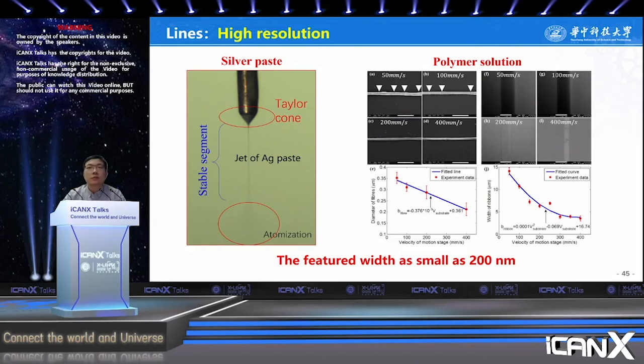However, for the honey-like solution, one can use both the stable segment and the high-speed motion stage to directly write pattern. And at the same time, the high-speed motion stage can further reduce the diameter of the jetting and easily reach sub-micrometer, such as 200 nanometer. Another important feature is to control the cross-section shape from the circle. This is circle fiber to thin film by adjusting the distance between the nozzle and the substrate.